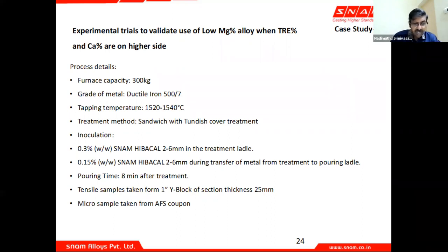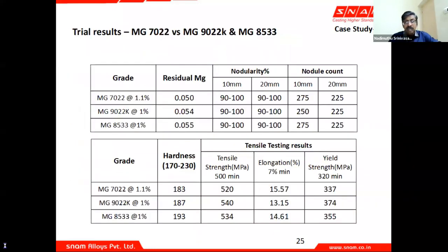The same was used in the post-treatment also. In the pouring time, we maintained it within 8 minutes, which is recommended. Tensile samples were taken from a 1-inch Y block of section thickness 25 mm, and the micro samples were taken from the AFS coupon. And these are the trial results. So if you look at the residual magnesium, it is the same. But of course, here the addition rate is 1.1. We wanted to see how it is comparable.